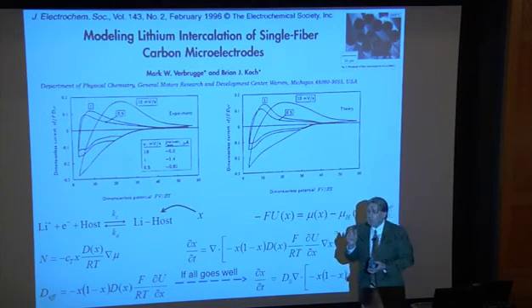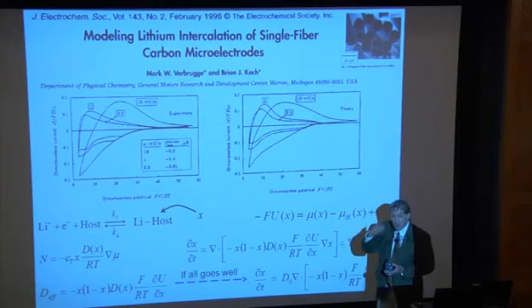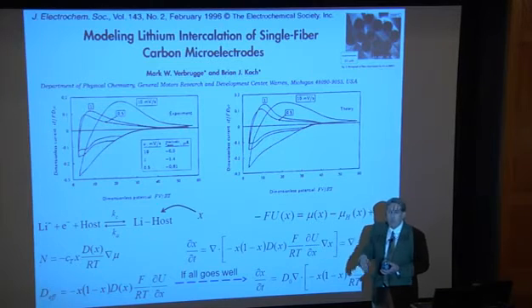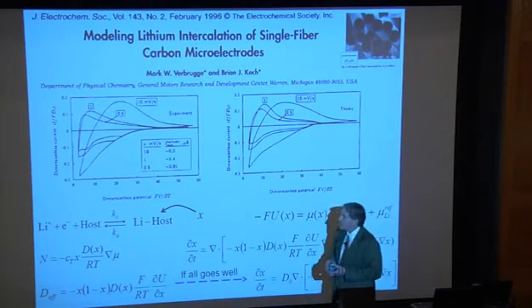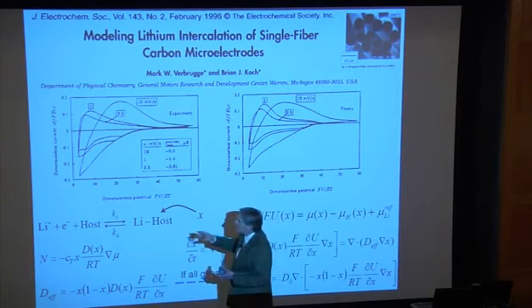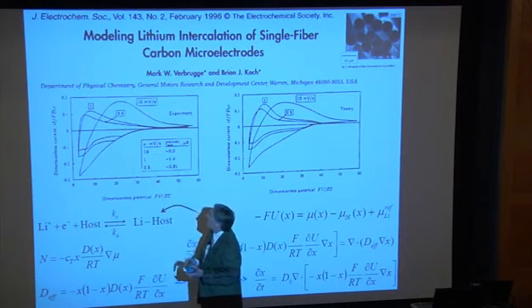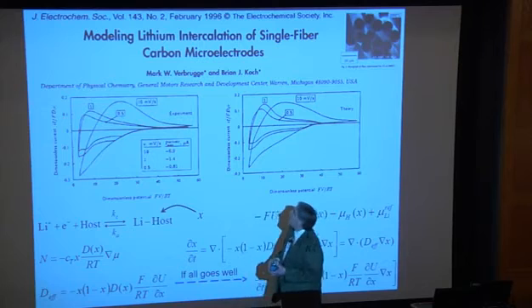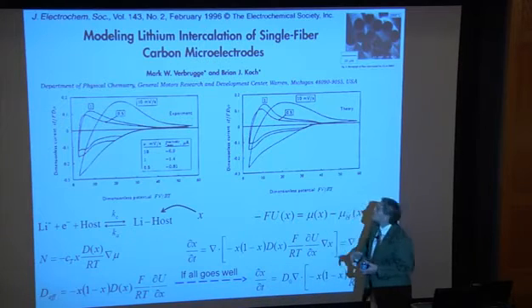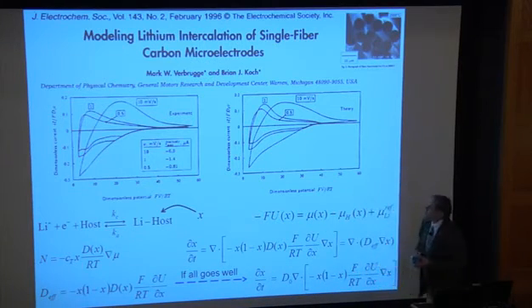These are largely single-phase systems. You can see this by a sloping open-circuit potential curve, which is very similar to a sloping free energy curve versus composition. And so here are experiments for cyclic voltammetry at 10 millivolts per second for a lithium single fiber electrode. There's some schematics of the single fiber shown up in the upper right.